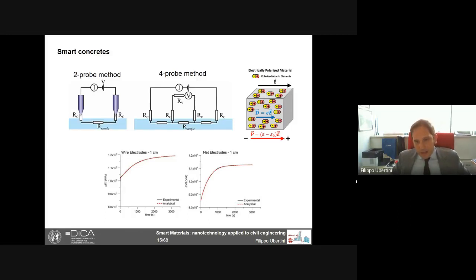So let's go to measurements. To measure the electrical resistivity of smart concretes, from the literature, we have two approaches, the two-probe method and the four-probe method. Both are direct current approaches. And the big problem we have in applying those methods is that since the material is a dielectric material, we have polarization. So typically we have an apparent increase in electrical resistance, like you see in the bottom diagrams, with time, because the material charges under application of a constant electrical field.